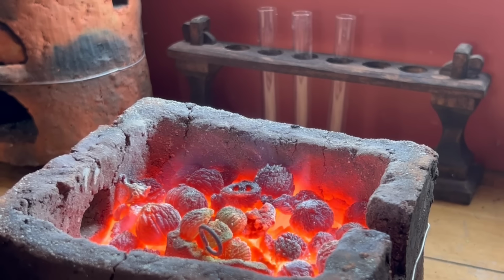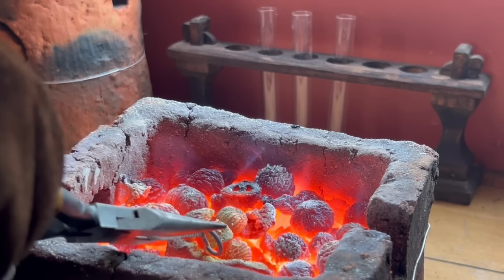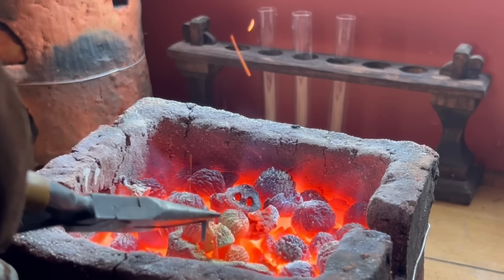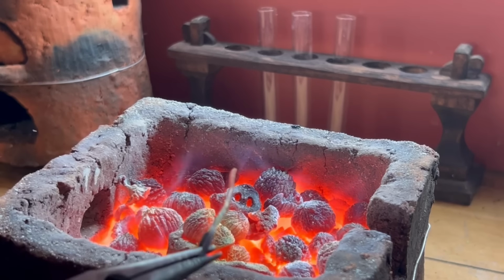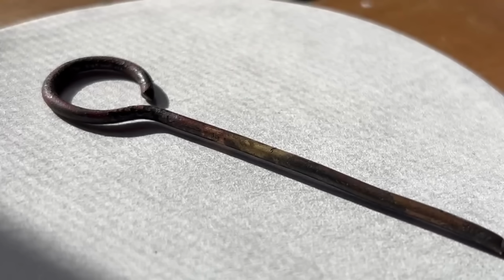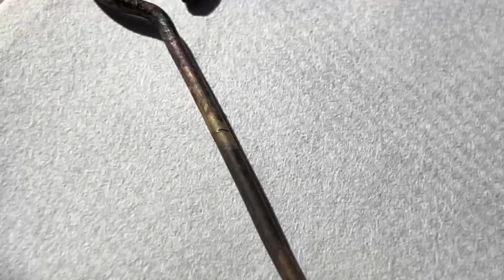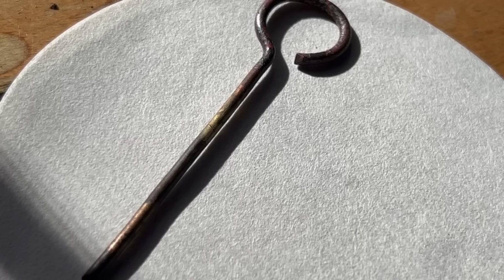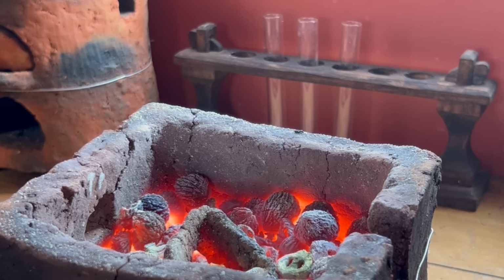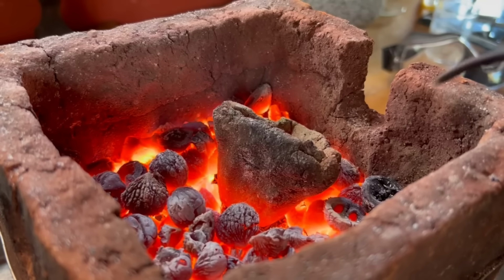After a short while, I uncovered the furnace again and pulled out the copper wire to see if any changes had taken place. On cleaning off the surface a bit, I could make out an encouraging streak of golden metal, though interestingly, the yellow color only appeared in the upper middle of the copper wire, where it had been exposed to the material I added halfway through, while the crucible was already hot. Unfortunately, I was completely unsuccessful at getting the calx to reduce, much less fuse together into a unified body.